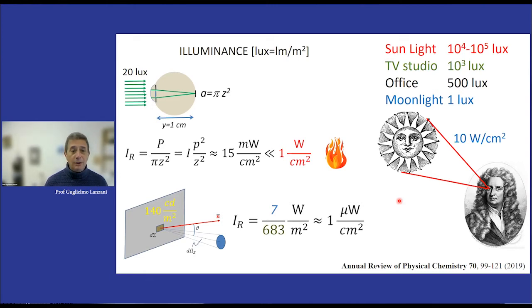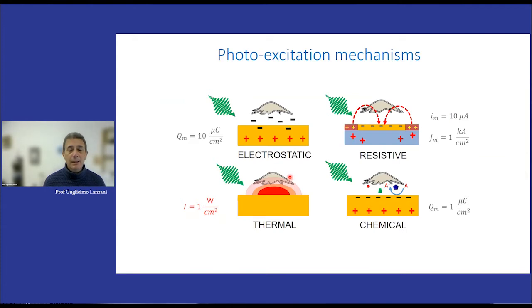Because this is the highest energy that we use in our experiment on the retina, you see that it's still two orders of magnitude smaller than the minimum energy to get a thermal effect. So we think we can exclude the thermal effect, which makes a lot of sense because it cannot be thermal in general. But anyway, it is excluded.